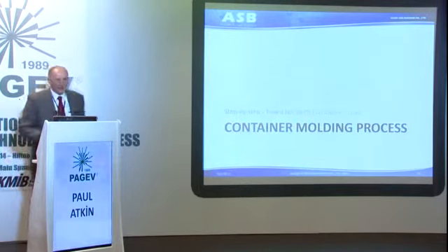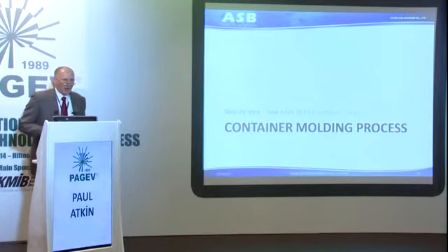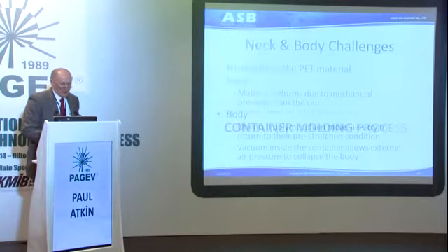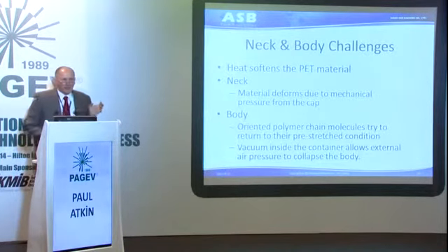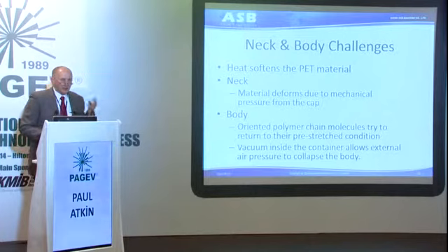Okay, so that's so much for the filling process. Look at how the containers are made, because there is a special process here. The challenge we face is that heat will always soften the PET material. In the neck, that will cause distortion as soon as we put the cap on. In the body, the material itself is trying to shrink back to its original form, and vacuum that's generated inside the container will lead to distortion and collapse of the container. So we have to fight against these things.